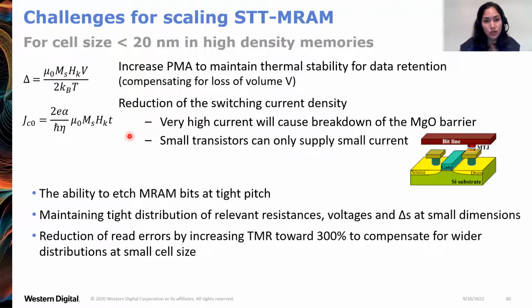We need to have low switching current because very high currents will cause breakdown of the MgO tunnel barrier and we'll have an endurance problem. But also, as I described, STT-MRAM cell is one tunnel junction to one transistor, and very small transistors can only supply very small current, but yet we need enough current to flip the free layer magnetization. So this is a very difficult trade-off for anybody working in MRAM, this trade-off between thermal stability for retention and low switching current. Okay. The other challenge is this one here is the fabrication challenge.